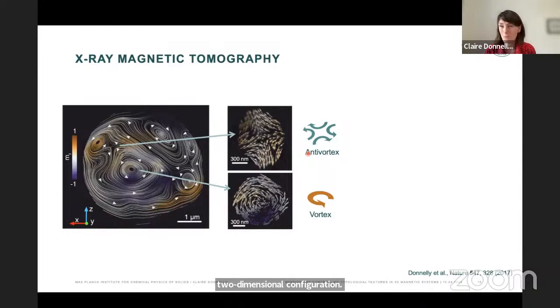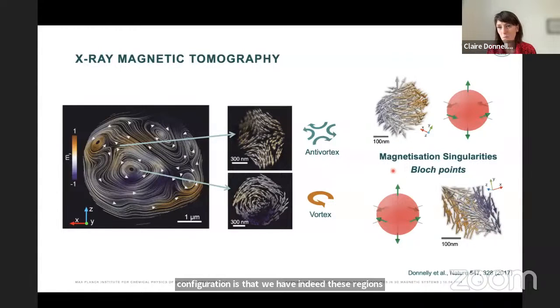But what we can see actually when we really take into account the three-dimensional volume of our configuration is that we have indeed these regions where the topology abruptly changes, and we see these Bloch point singularities, so Bloch points and anti-Bloch points that are effectively points at which the magnetization vanishes and associated with abrupt changes in the topology of our configuration. So these Bloch points had been seen or had been predicted, I think in the 1960s already by Feldkeller, but it wasn't until we had this technique that we were able to image them directly in real space. So we have now static imaging, but we can go further than that.